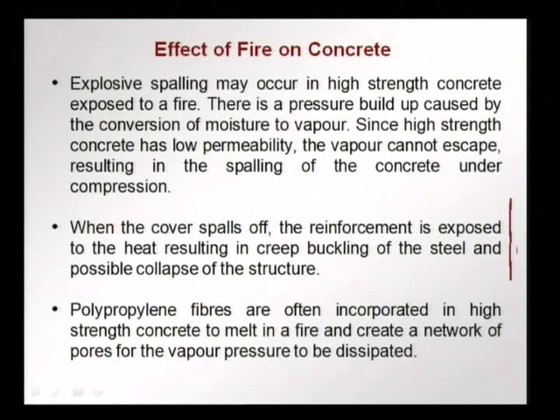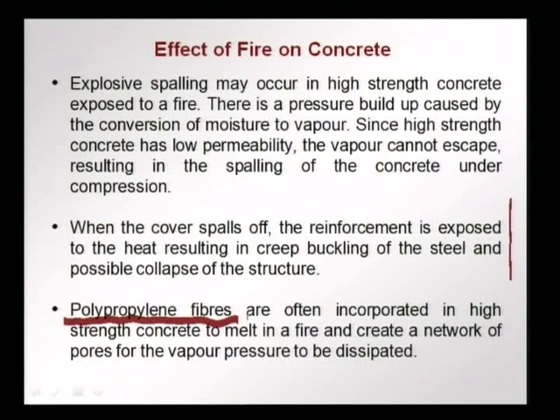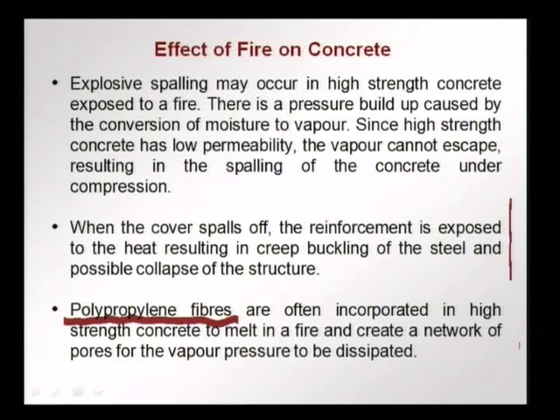A popular way to prevent spalling is the use of polypropylene fibres. These fibres melt at high temperatures and leave pores through which water vapour can escape — acting like a safety valve. As pressure builds up, the fibres melt, facilitating escape of the water vapour and dissipating the pressure. The fibres do not increase strength; they create porosity for vapour escape. Structural integrity is maintained, preventing collapse, and after a fire the lining can be repaired.